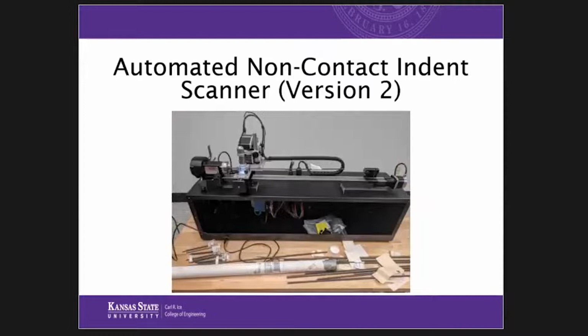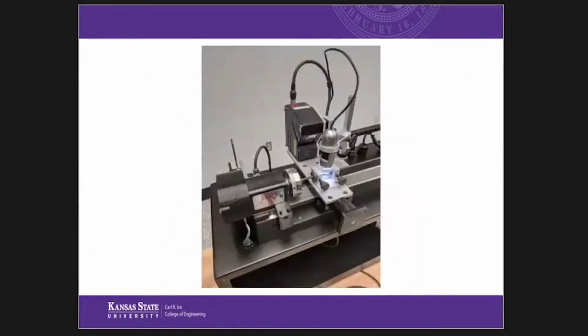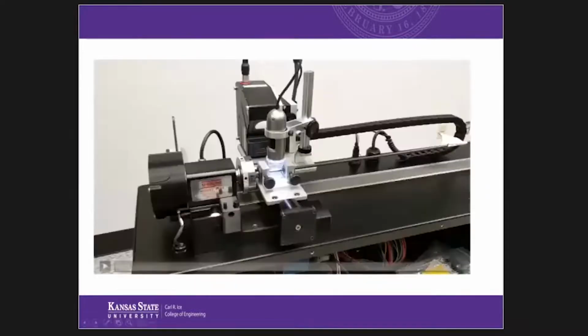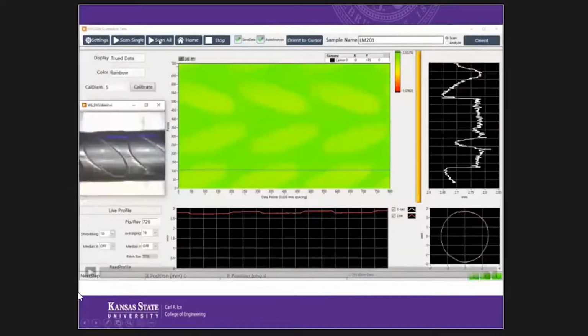Here's version 2. It looks very similar. The difference is, on a close-up look, we use a more powerful laser, and we've also added a digital microscope to capture pictures of the individual indents just for reference. So this is a video of how this actually works. We spin the wire and we're measuring it with the laser.